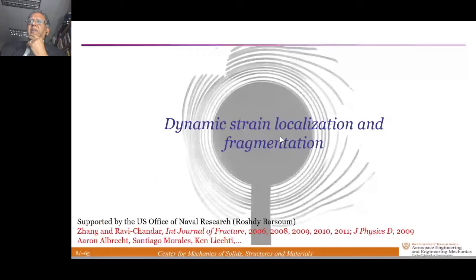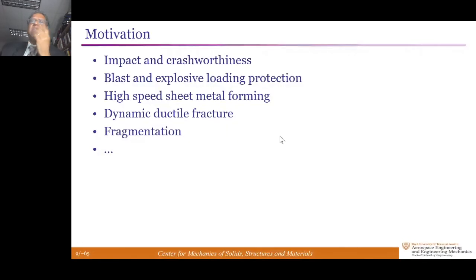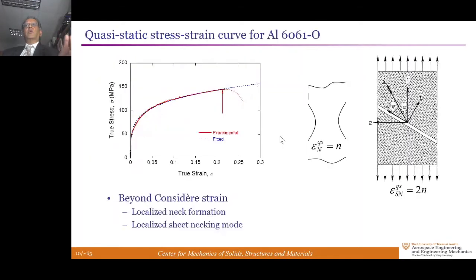It's a problem that arises in a number of applications in impact, blast, and high-speed metal forming, and so on. The main idea is, for a ductile metallic material, if you do a quasi-static test, pretty much everybody knows that there's an inelastic response followed by localization at the Considère strain, and beyond localization, the bulk of the specimen doesn't deform, only the localized region deforms further, leading to eventual failure.